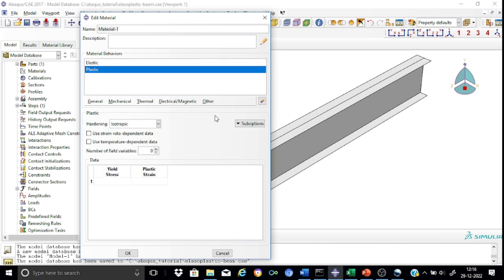Now let us populate the plastic properties of the material. The yield stress will be 355 MPa, and the corresponding plastic strain is 0 (no plastic strain component here). At the ultimate stress of 470 MPa, we have a plastic strain component of 0.178. Note that 0.178 is the total strain of 0.18 minus the elastic strain of approximately 355/E. So we have defined both the elastic and plastic properties of the material.